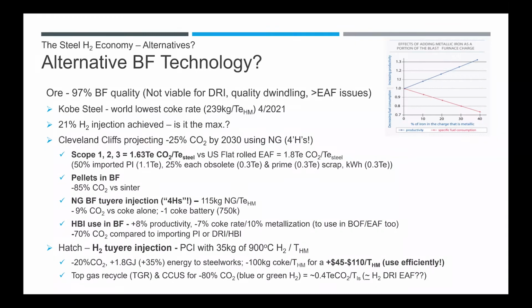Natural gas blast furnace tuyere injection at 115 kilograms of natural gas per ton of hot metal has reduced CO2 9% versus coke alone, and that's saving them 1 coke battery a year. The HBI in the blast furnace has increased productivity 8%. Coke rate has reduced 7% for every 10% of HBI input. And they're saying 70% reduction in CO2, of course, comparing to imports of pig iron and DRI HBI.